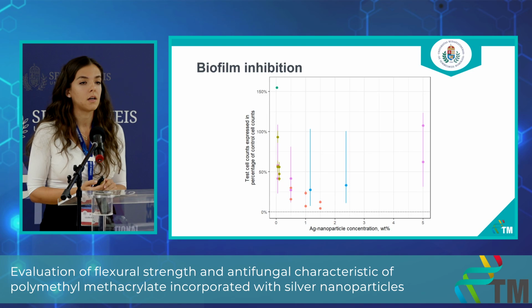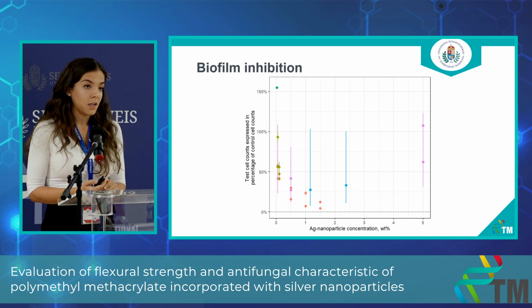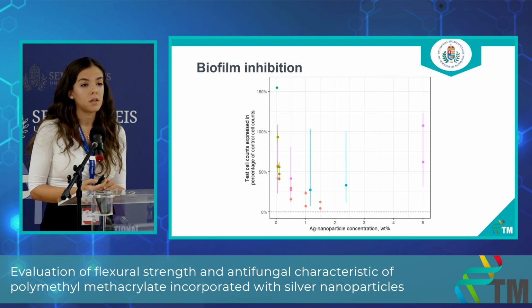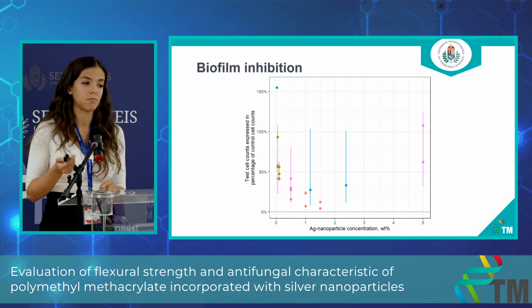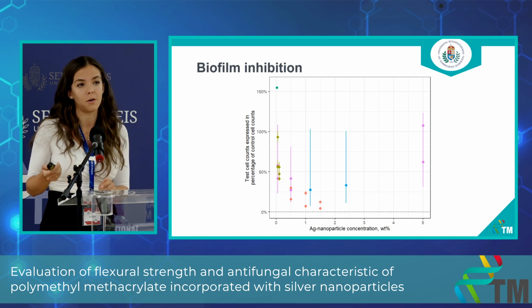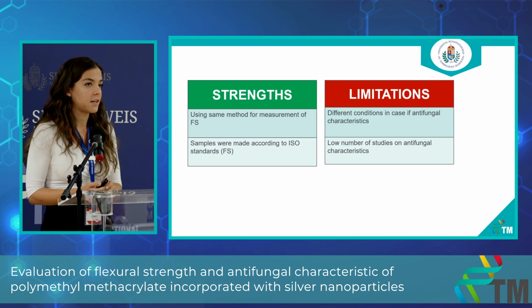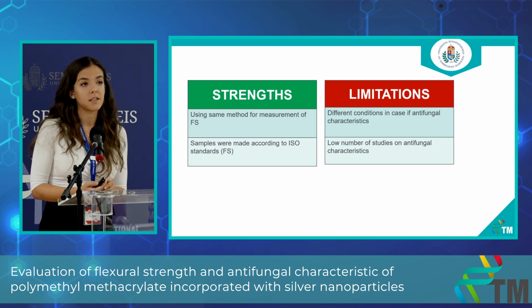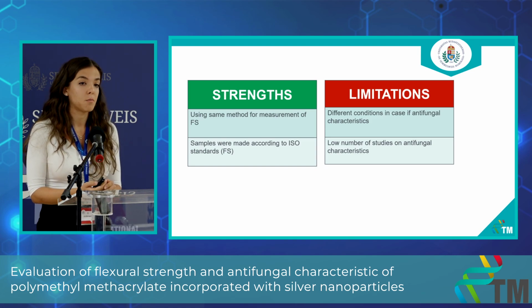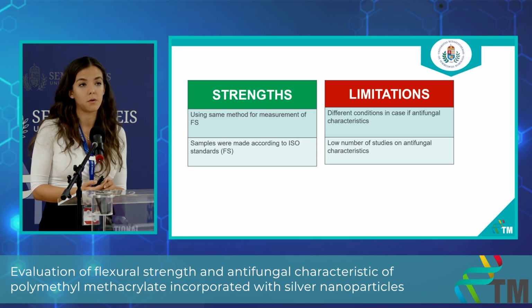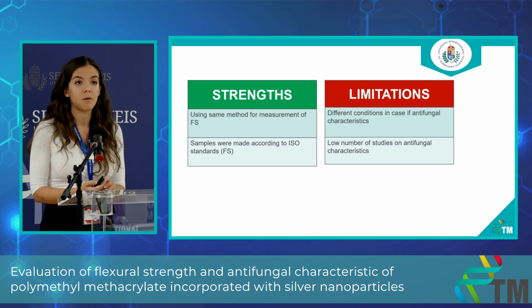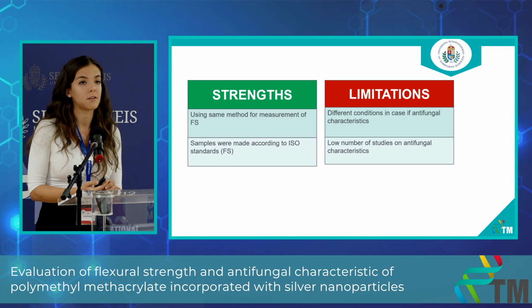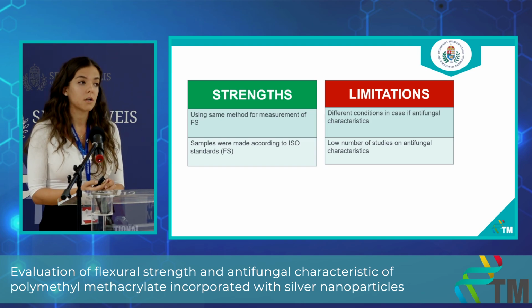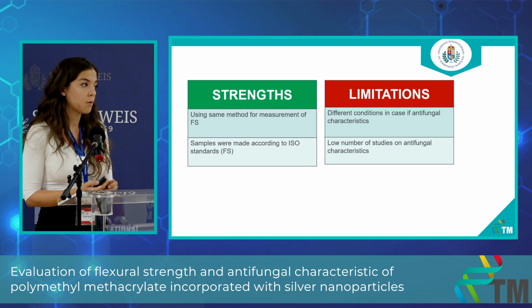And here we can see that the number of cells is significantly decreased in the silver nanoparticle incorporated samples compared to the control group. What were our strengths? In case of flexural strengths, these studies used the same method for measurement, and samples were made according to ISO standards, and there were some limitations as well. In case of antifungal characteristics, the conditions were different and the number of studies was low.